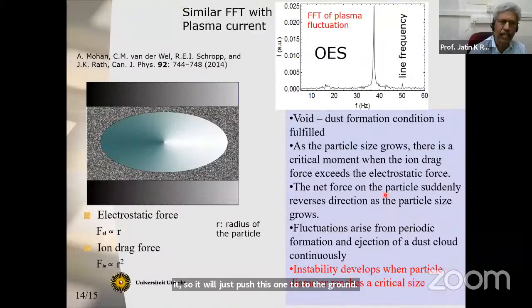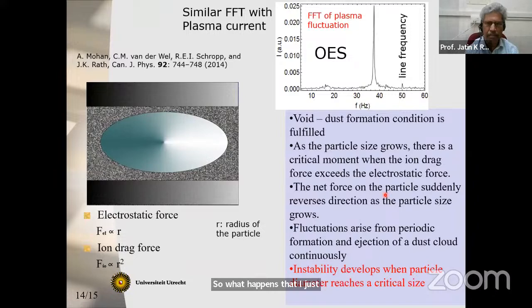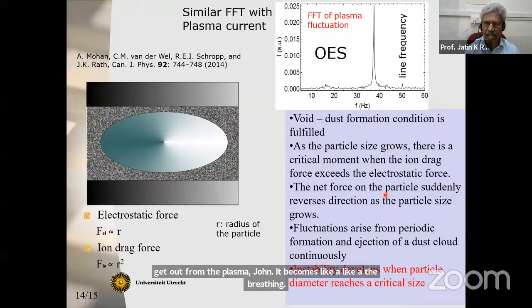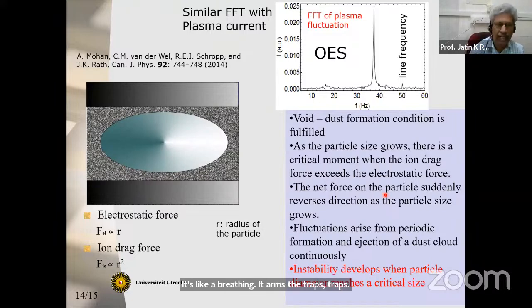So what happens is that particles will form. They become some size. Once that size is reached, it will go to the wall. Again, another new particle will form. Again, the size becomes bigger and bigger. Once the radius becomes some size, it will get out from the plasma zone. It's like breathing. It forms, detraps. It goes on like this.